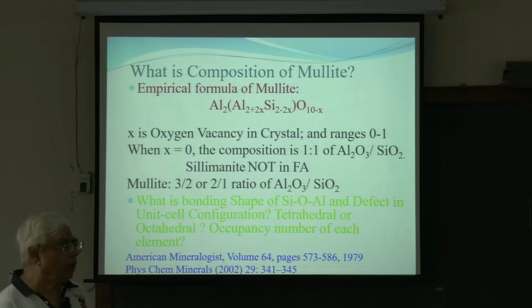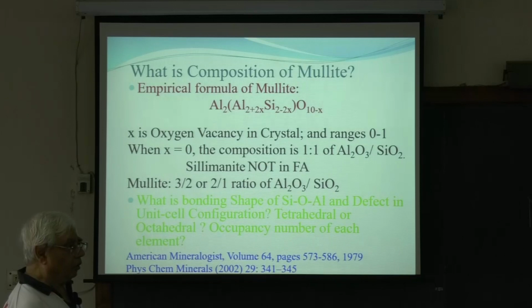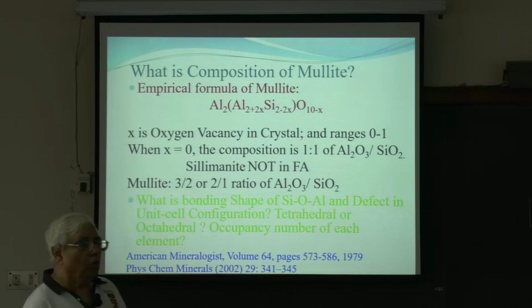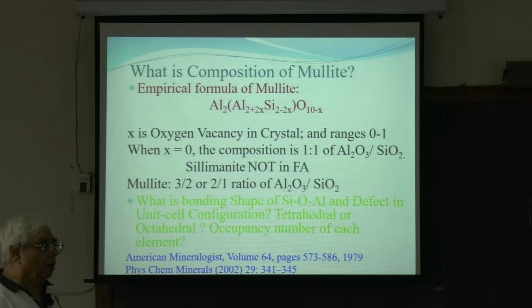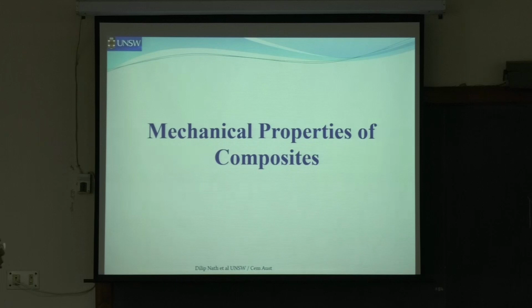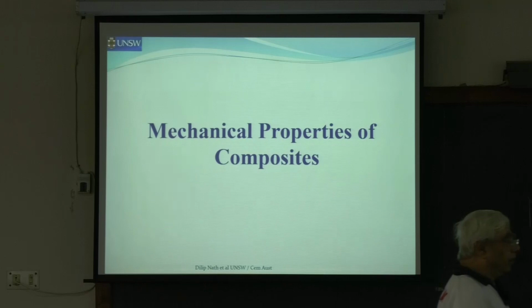So presence of mullite, till that information I didn't think much of mullite. I thought it's just part of everything. But then when we showed that those two compositions, which have the highest real and highest imaginary dielectric constants, did not show any mullite on the X-ray diffraction pattern, those few graphs, particularly the X-ray, are very interesting.